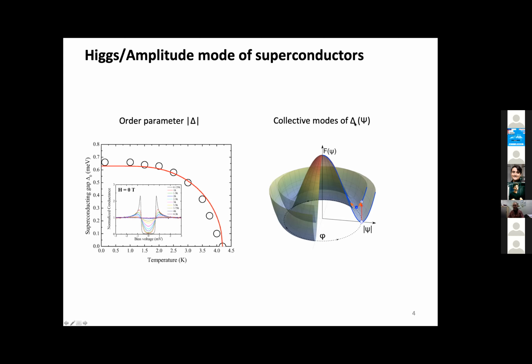So if we think of the complex order parameter of a superconductor and we draw now the free energy surface as a function of this complex order parameter, then this gives rise to this famous Mexican hat. And here we have two types now of collective excitations. One would be an oscillation here of the phase that is dissipationless. So in that sense, that is the famous Goldstone mode in a system. And the oscillation here along the rim of this Mexican hat, these are oscillations of the real part of the order parameter. So this would be really an oscillation of what we measure as a gap size in the system. And these are the famous Higgs oscillations in the system.